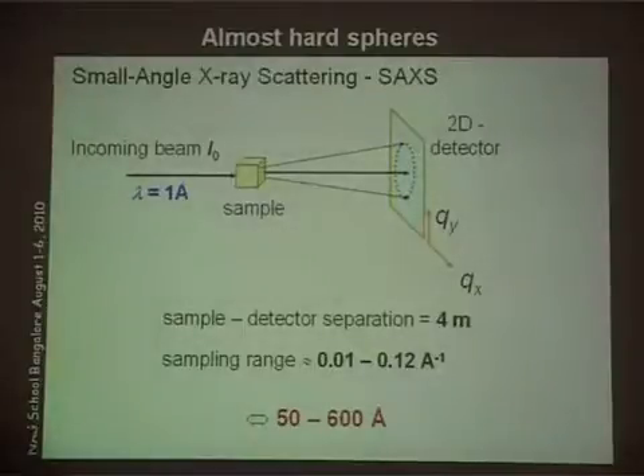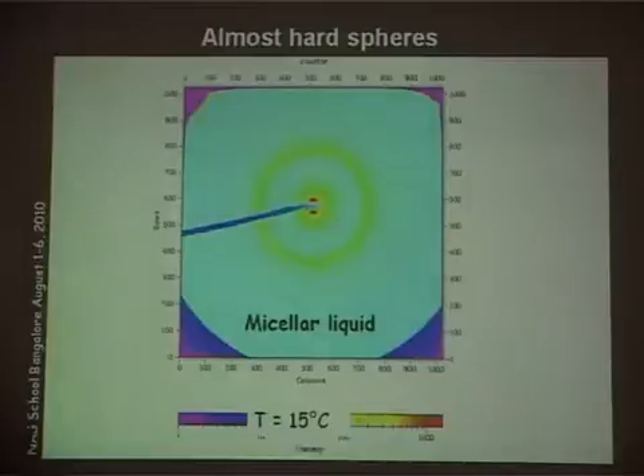Okay, now the first thing that we did was look at how big our micelles are, in the micellar liquids. What you typically obtain is what we call a diffuse ring. It is very diffuse in the sense that the higher orders are barely visible, because it is a very mobile system. But you do a static scattering and you average over all positions. From this liquid ring, we get an idea of how big the micelles are. This is at 15 degrees in the liquid system.